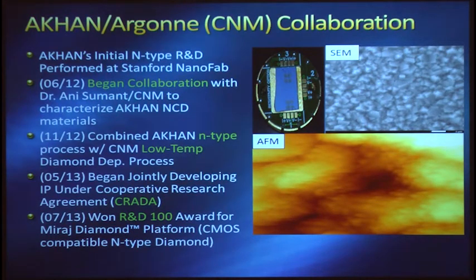Initially, we had pioneered our R&D capabilities utilizing leading university nanofabs, such as Stanford's nanofab facility. But earlier last year, we began to collaborate with the Center for Nanoscale Materials, and particularly with Dr. Ani Sumant, to characterize the AKHAN materials. Shortly thereafter, we combined the AKHAN N-type process with a really neat technology developed at Argonne, the ability to deposit diamond at very low temperatures, approximately 400 degrees C. This is important because now we can put diamond directly on silicon without destroying the underlying circuitry.